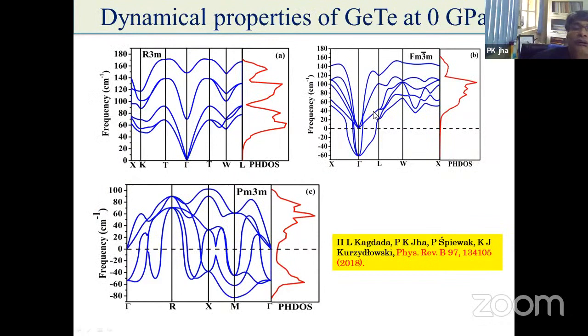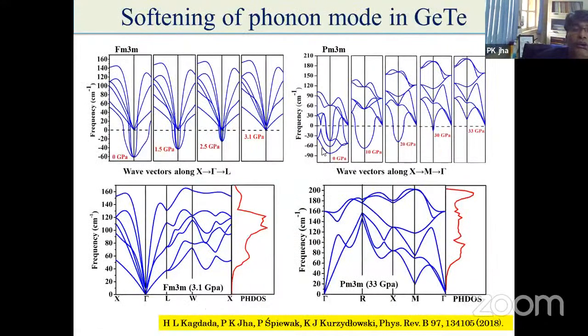So you can see from the phonon dispersion curve, rhombohedral is stable at ground state, while the cubic is not, or similarly the orthorhombic is not stable, right? Because of the imaginary phonons in these 2 cases. Of course, these 2 can be made stable by applying pressure, and you can see that Fm3m, the cubic, which was unstable at 0, becomes stable at 3.1 GPa, right? And that is the phase transition pressure for Fm3m also, from rhombohedral to cubic. Similarly, for the Pm3m, from 0 you have full imaginary phonon, but at 33 GPa, which is experimentally 34.5 GPa, it is stable.